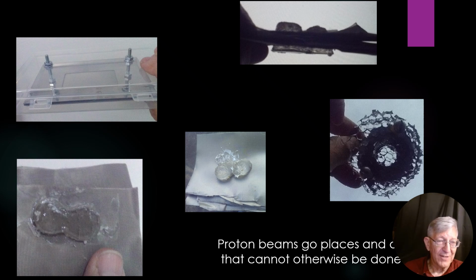On the left-hand side at the top, what you see is a plastic box, and in that plastic box we have mounted a metal frame. Actually, it's two pieces, and between those two pieces we have compressed a stack of aluminum screens. These are very fine screens, so you can't see the holes looking at them under these conditions, but they're tiny little holes in these aluminum screens. And what we did, we put the screen between the two plates, held it all rigidly in place, and then we filled the box with resin, and then we pulled a vacuum on the box so that the air bubbles that are trapped in the aluminum screens would come out and the resin would go back in.